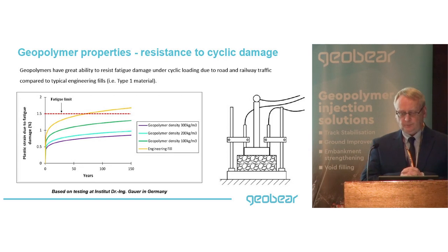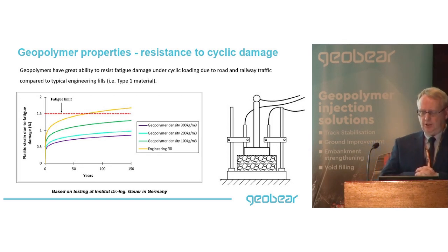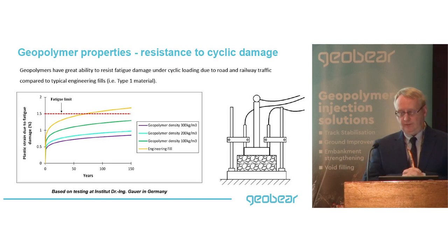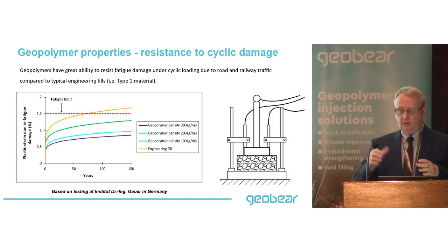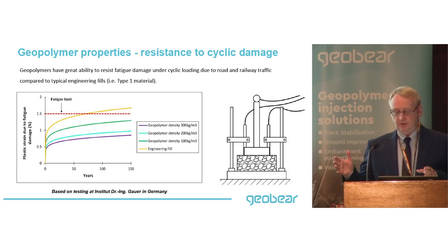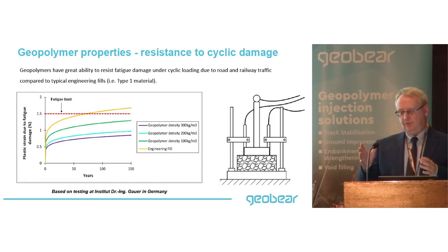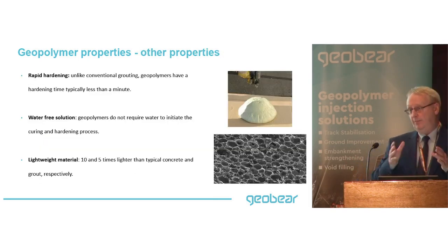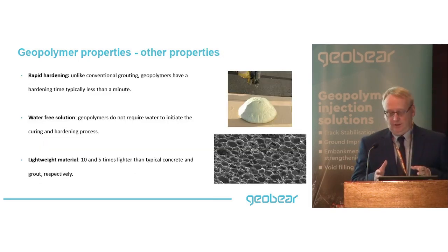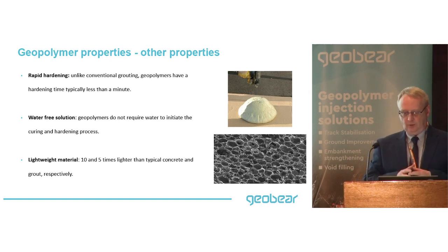Unlike conventional grout, geopolymers have a hardening time typically of less than a minute. You saw the reaction go from liquid to solid in a matter of seconds. The full strength is normally achieved within 24 hours, and probably 90% of the strength in a matter of 1 hour. So they rapidly harden, which is quite different to conventional grouts.